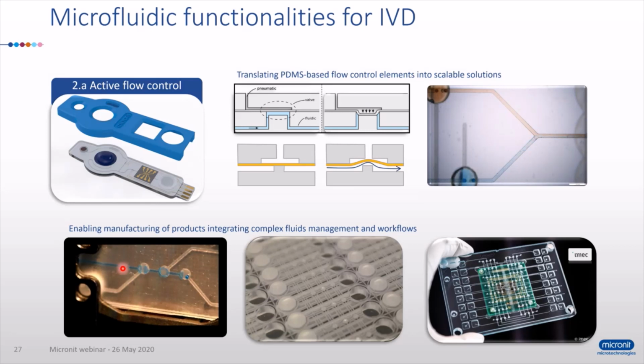And here we can see the blue layer is the fluidic network, and the white layer is the pneumatic network, which is used to actuate the valves. 3 valves in series, actuated in series, provide flow, so they also provide a pumping function. And in this case, we have also microstructured a nozzle at the exit valve, which can be used to dispense very accurate amounts of reagents, for example, to a reaction vessel.